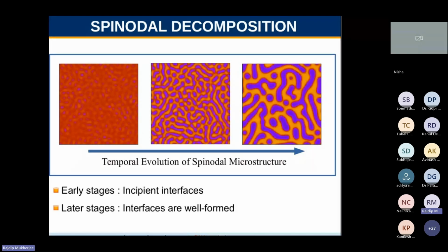And you can see initially there are incipient interfaces. You cannot tell exactly what the interfaces are, but then well-connected interfaces will form. And this is also known as a bicontinuous microstructure. You can go through the purple phase and reach the other side of the system or the orange phase, right? So this is a 50-50 kind of composition. This kind of microstructure is very important in different alloy systems.